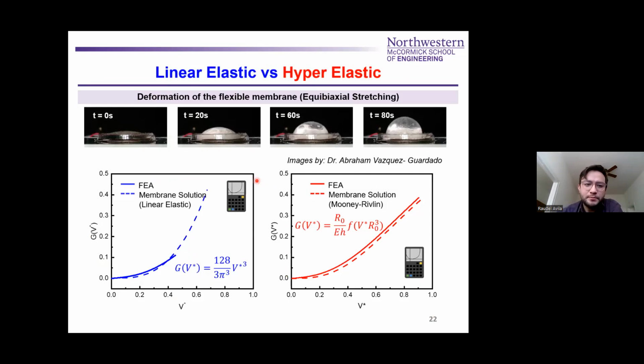So, for example, if we assume that our membrane behaves linear elastically, in this case, we're saying that the stress is related to the strain by the equibiaxial stiffness of your membrane. Now, this is just a very basic assumption to show how we can derive a very simple approximation of the membrane deformation. So here, if we take a look at the images on top, we see that at time 0, we have a flat membrane, then at time 20, 60, 80 seconds, it eventually evolves into this spherical cap.